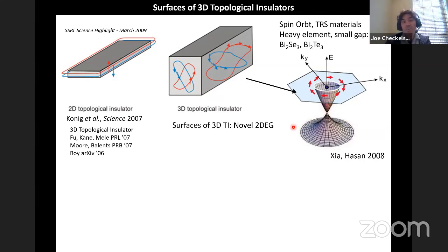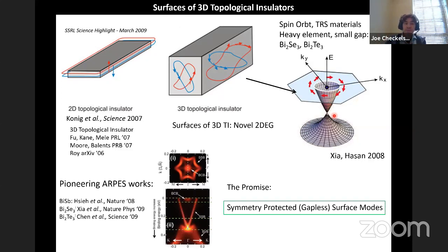And again, the idea here, much the same way that disorder wouldn't be able to ruin this edge mode, disorder on the surface wouldn't be able to open, say, a gap in this spectrum. And that was something that was borne out using different spectroscopic techniques, where basically what people were able to see in these different heavy element small gap semiconductors is modes which were attached to the surface and had this linear-ish spectrum, which they should, at least near this crossing point, and basically didn't have a gap, right? And the idea that this was predicted by time reversal symmetry was giving what people refer to as a topological protection, meaning that you could move around the shape of the band a little bit, but you weren't able to open a gap.